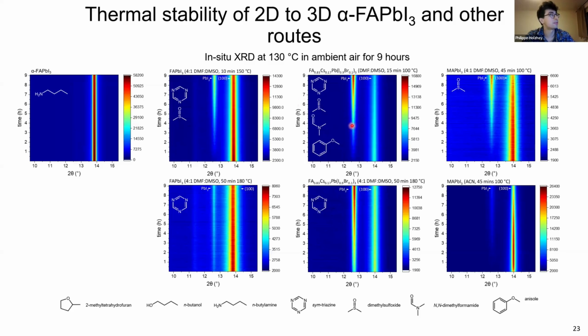And then for the other films, you see the residual solvents. So for example, here we have FAPI with 4:1 DMF DMSO, which was annealed for 10 minutes at 150 degrees. And that shows some sym-triazine and DMSO and some lead iodide forming during this test. And then the moment we add the cesium phase, we see that there's more lead iodide forming, but we also find other solvents like DMF and the anti-solvent.